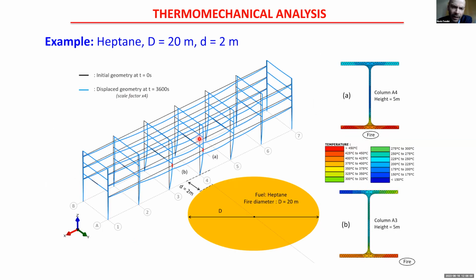Here is an example of the outcome of a thermomechanical analysis. Here is a heptane fuel with fire diameter equal to 20 meters. Here you can see the deformed shape of the structure, and here the thermal field in the columns. Of course, there is a large thermal gradient in the structural element because of the localized fire.